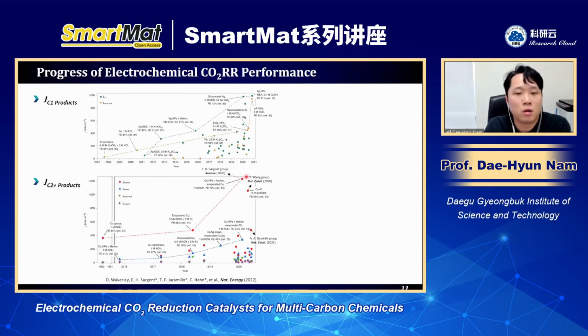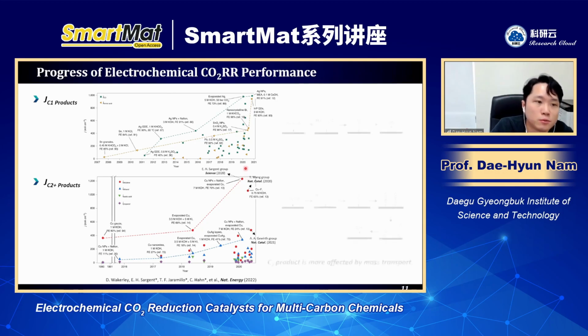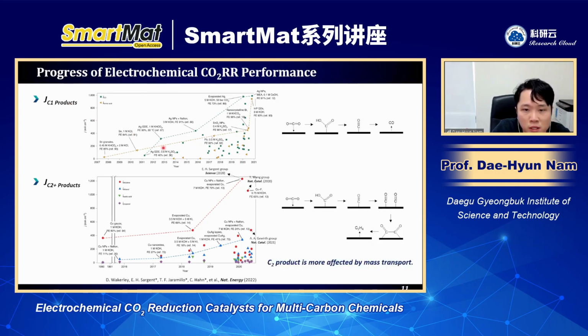This slide also showed some progress of CO2R in terms of the partial current density, which I mentioned. In the case of the C1 products, because this paper was published in 2022, if you look at this year, the partial current density for C1 products such as CO or formic acid has already come close to 1 ampere. But in the case of C2 products such as ethylene and ethanol, there is a lot of void. It means that it is very difficult to get high current density for C2 chemicals.